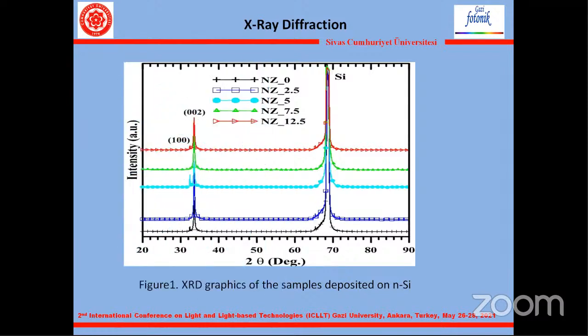X-ray diffraction. In the figure, the crystal structures of zinc oxide thin films doped with different nitrogen percentages on the N-type silicon are shown by X-ray diffraction. X-ray measurements were made between 20 and 90 degrees in a step range of 0.02 degrees. Accordingly, it has been seen that the films are generally zinc oxide with 100 and 002 orientations. As shown in the figure, the 100 orientation was not observed in the sample with only 2.5% nitrogen.